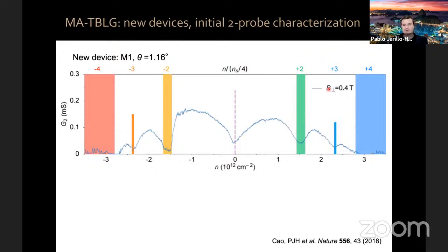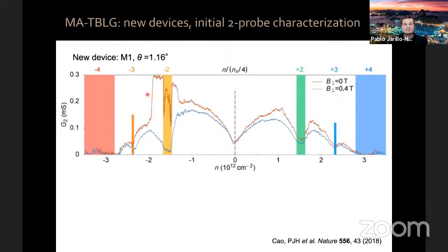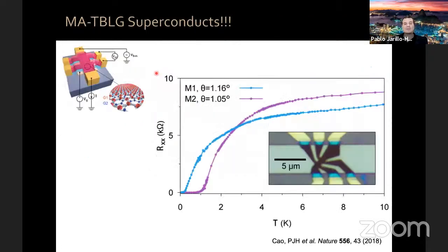And then when we remove the magnetic field, you can see that things go crazy around 2 holes per moiré unit cell. In fact, if we now switch to our 4-terminal geometry in order to characterize the sample better, what we see is that magic angle twisted bilayer graphene superconducts. These are data for two devices. The resistance versus temperature goes down by several orders of magnitude below our noise measurement floor. This thing is a two-dimensional superconductor.